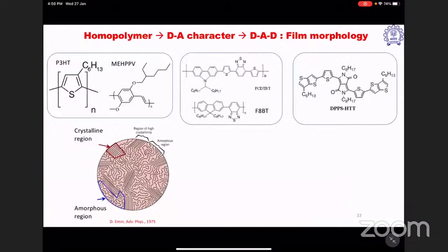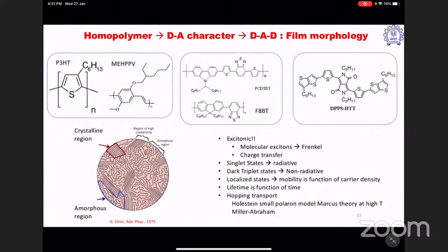But when you make a thin film out of all these polymers, in the thin films you are going to have various kinds of geometries. Some of them will have crystalline regions, some can have amorphous regions, and the percentage of these amorphous and crystalline regions is going to dictate lots of interesting observations related to these materials, being organic, low density materials. The primary excitation, whether electrical or optical, is always going to be an exciton. And that exciton, being in this kind of disordered system, is always going to be a Frenkel exciton, because it will be very much localized to the particular molecule where it has been generated.